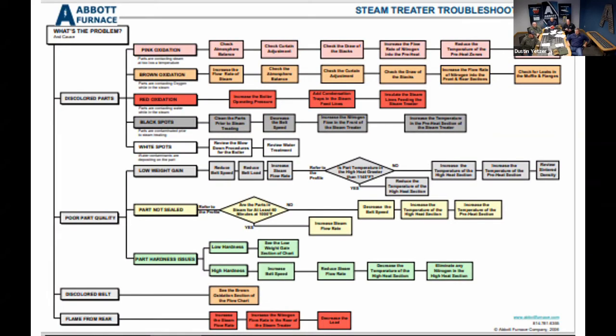So if there's actual droplets of water that are coming through the boiler, oftentimes that comes if a blowdown on the boiler, where you're emptying out excess residual water in the boiler, doesn't happen, you tend to see the droplets condense in the piping and then they come out. There isn't enough time for that to flash off into steam. So that can be a cause of red oxidation.